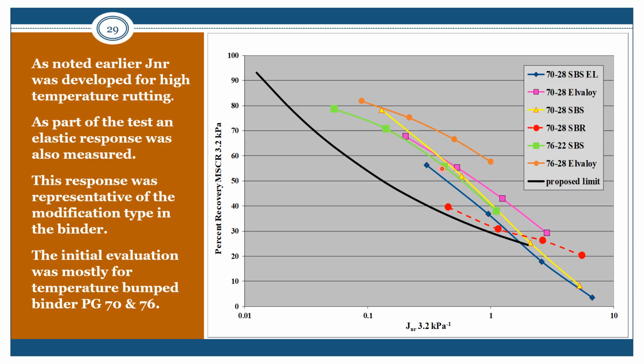And as we go down and lower the temperature, either it's 70, 64, or 58, now you can start to see the Jnr values start to separate out a lot more, depending on the base asphalt, because 76-22 is going to use a little bit stiffer base asphalt than the 76-28. And then you'll start to see that. So where you have almost the same Jnrs here, they start to now separate out at a little bit colder temperatures, and the percent recoveries start to come together.